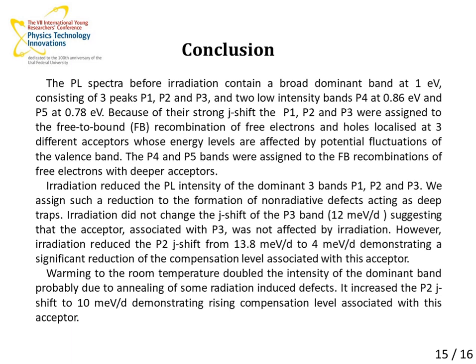However, irradiation reduced the energy shift of the second band from 13 millielectron volts per decade to 4 millielectron volts per decade, demonstrating a significant reduction of the compensation level associated with this acceptor. Warming to room temperature doubles the intensity of the dominant band, probably due to the annealing of some radiation-induced defects. It increased the energy shift of the second peak to 10 millielectron volts per decade, demonstrating a rising compensation level associated with this acceptor.